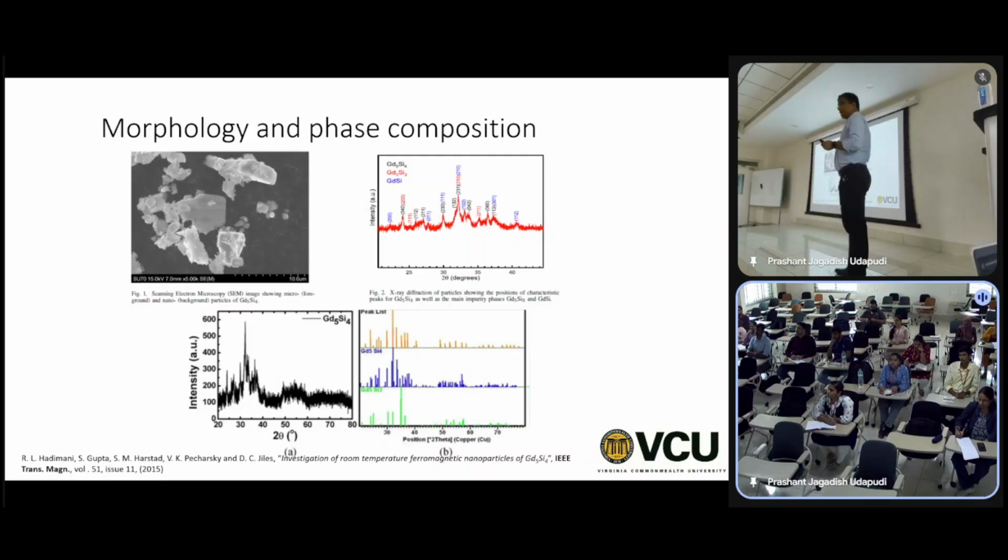So in this case, it emits an X-ray, and the energy of that X-ray depends on what orbit it is. That means if you know how much energy the X-ray has, you can know what material is in that sample. Okay, so that's how you can identify all the elements that the sample has.